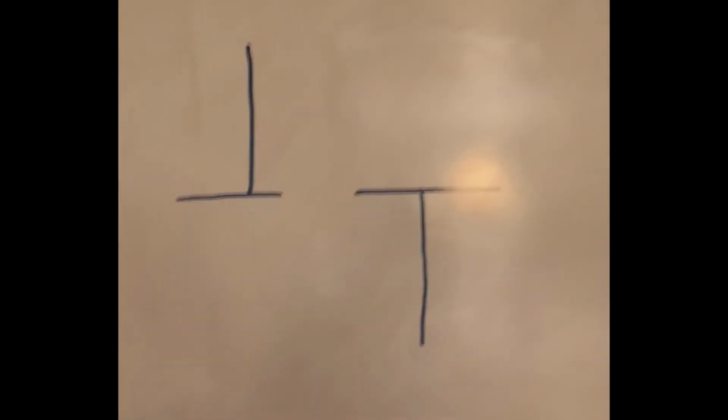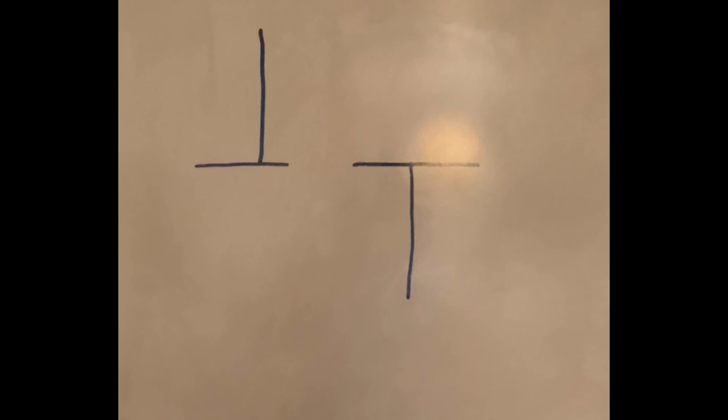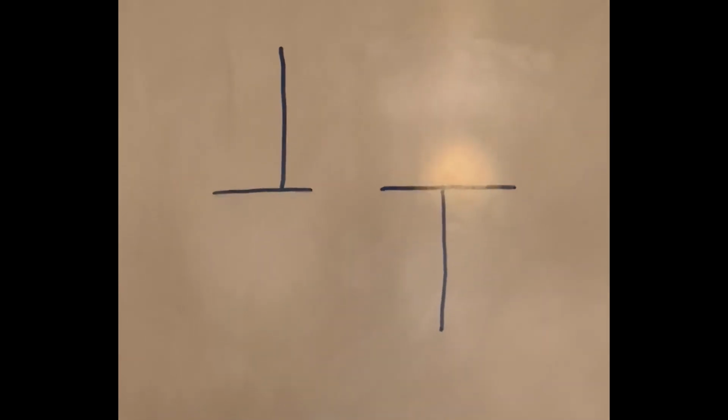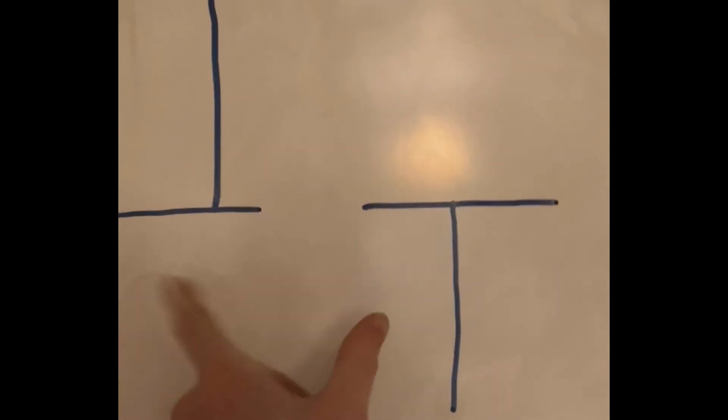Okay. So another scenario we can have is when we have two edge dislocations of equal magnitude and opposite sign. That is, their Burgers vectors are equal but opposite in direction. And when they're coming into close contact with each other on the same plane, they will attract each other and could potentially join and remove both.